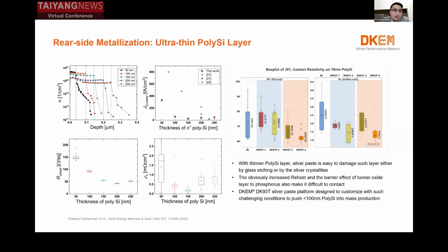The second thing we want to talk about for rear side metallization is the ultra-thin polysilicon layer. The industry practice is well aligned with academic results on the polysilicon thickness. The comfort zone of the polysilicon layer is between 100 nanometers and 150 nanometers. When we want to make a thinner polysilicon layer, we always observe two things, and it is a headache for metallization: the J0,metal increases and the contact resistivity increases at the same time.